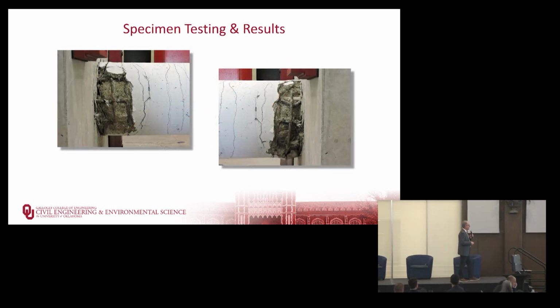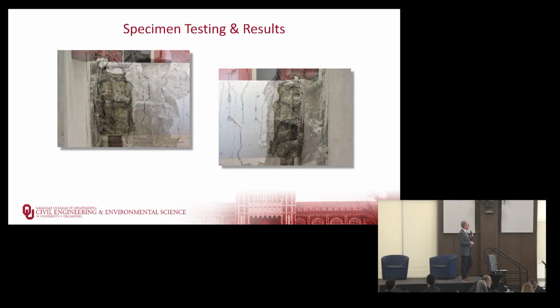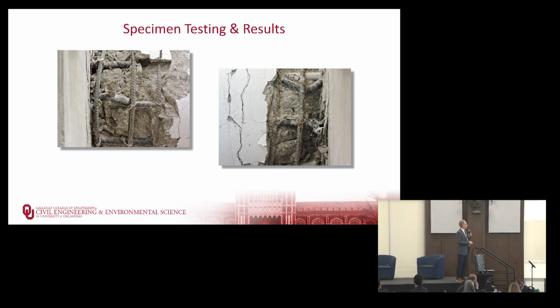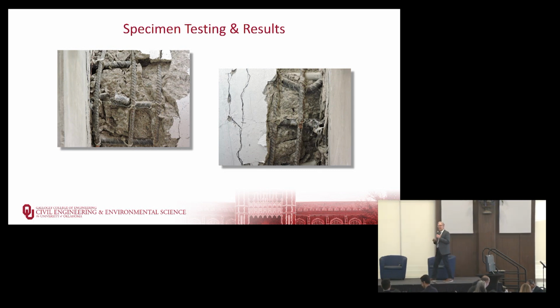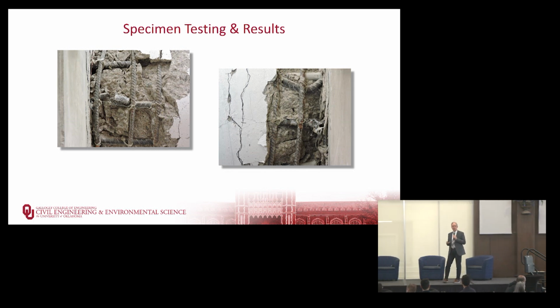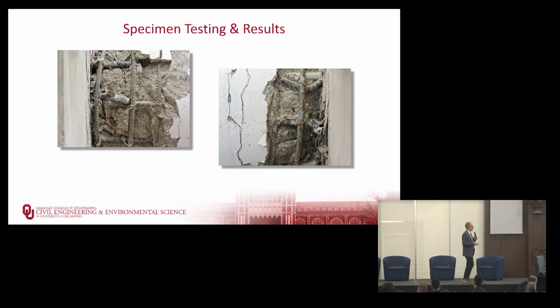So then we opened up the columns. This is our concrete column. We zoom in a little. Typical response, some of the longitudinal bars have buckled. Some of them had fractured. This one has fractured and this one has fractured. So very typical behavior. So again, we did that to make sure that our test setup was accurate for when we tested our new columns, and everything looked really, really good.